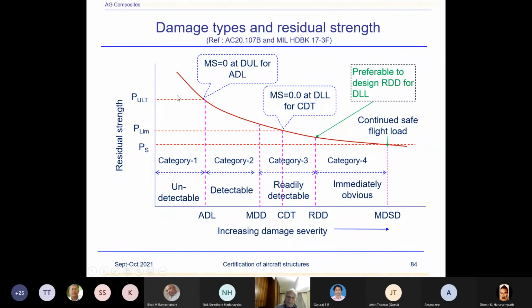And that is why we do the margin survey once after designing the structure, so that we can divide the structure into several zones for the repairability. In a particular zone, we'll say only a 1/4 inch hole is permitted. In another zone, we can say up to 1 inch. If in service the structure gets damaged and it creates almost a 1-inch hole equivalent damage, the airlines don't have to immediately repair the damage. They can put some high-speed tape, fly, and then during the next inspection interval they can repair the damage as a permanent repair. That is the advantage of this allowable damage limit. This is for the maintenance or repairability of the structure. We provide the guidance and divide the structure into various zones.